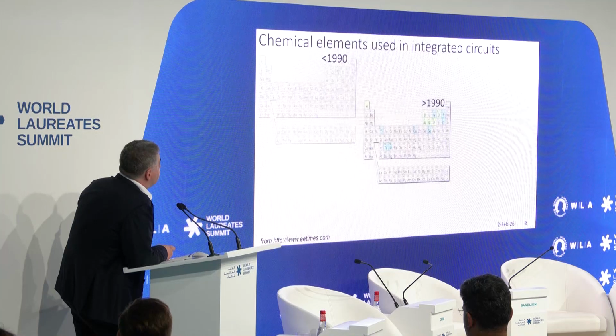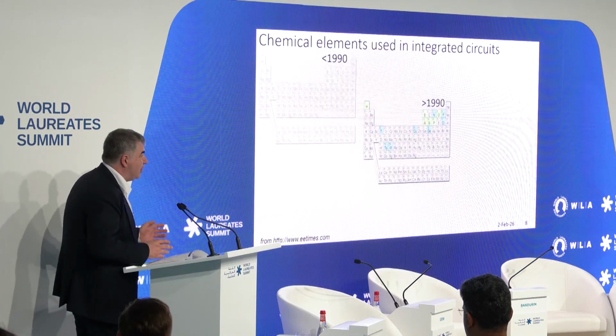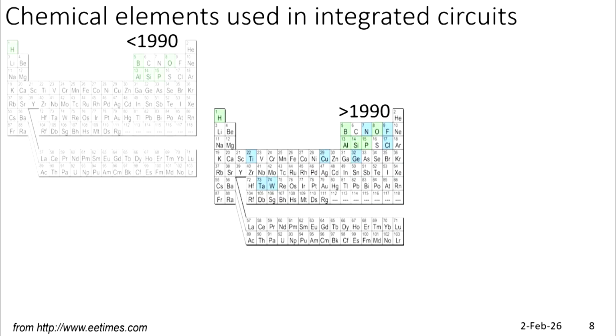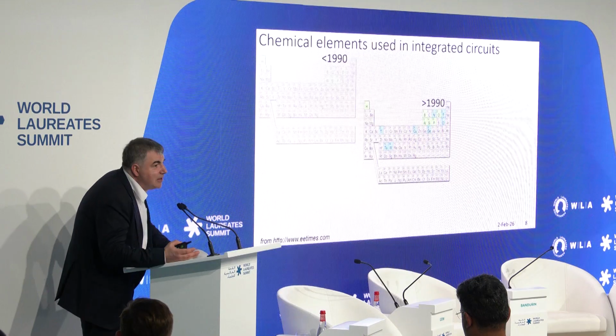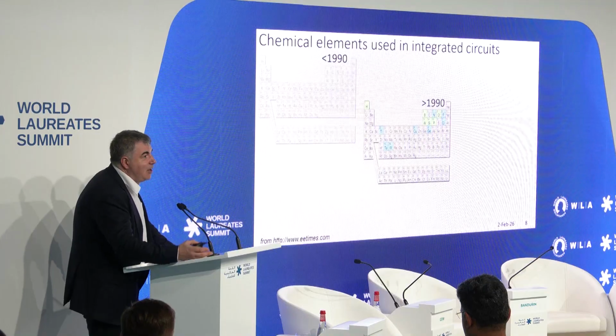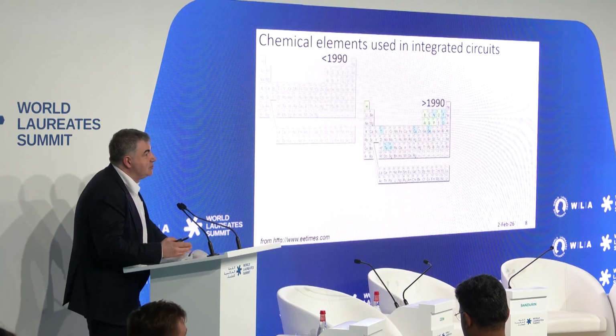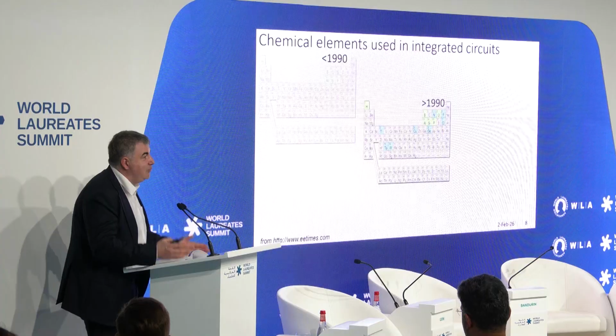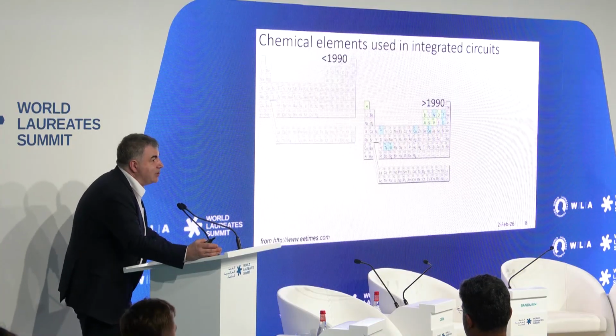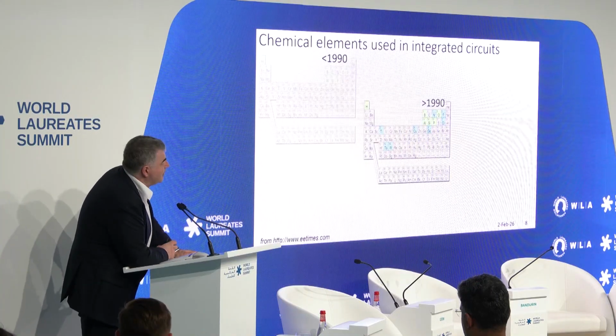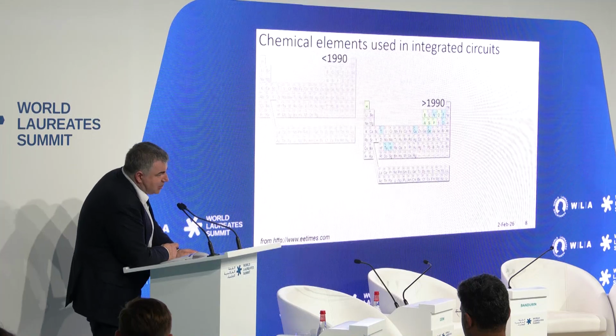Brilliant. Then after 1990, we needed to shrink our transistor a little bit more. So we had to use more conductive materials for interconnects. So we started to use copper. It immediately brings a problem that copper diffuses into silicon. So you need a diffusion barrier. You need some work function matching materials. Apart from copper, we had to add quite a few other elements as well, but still a manageable technology.